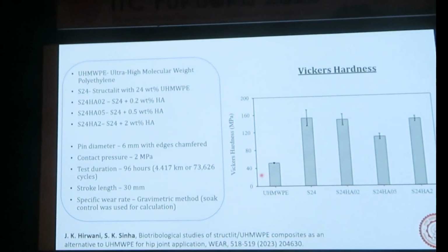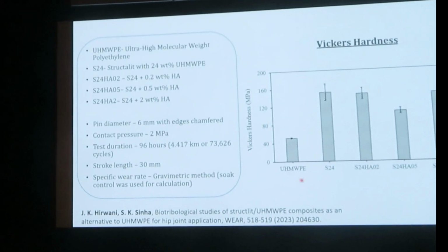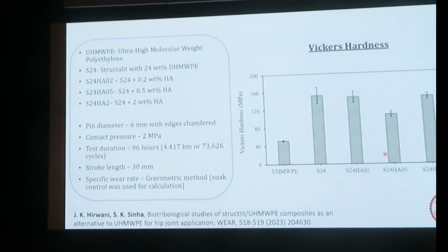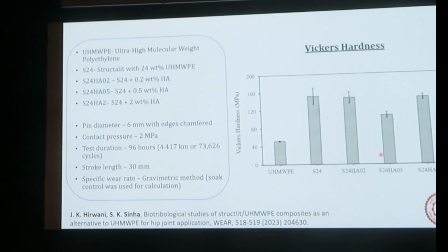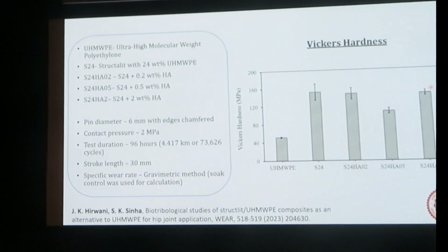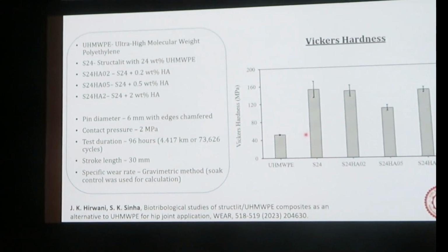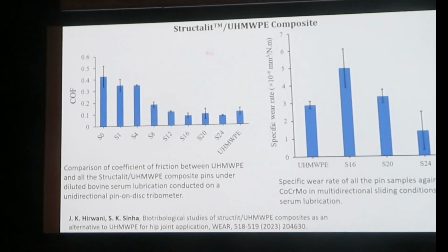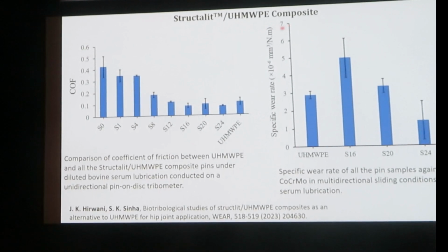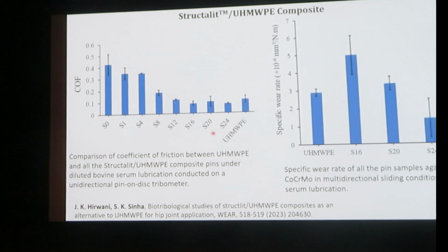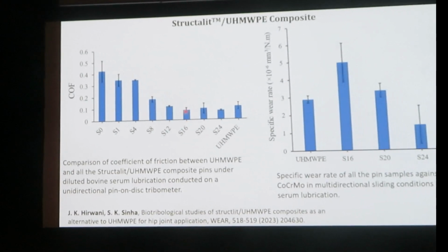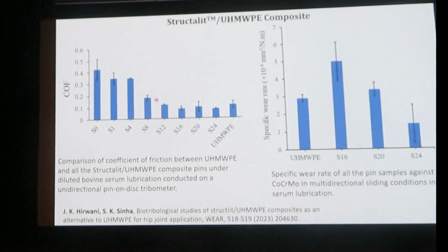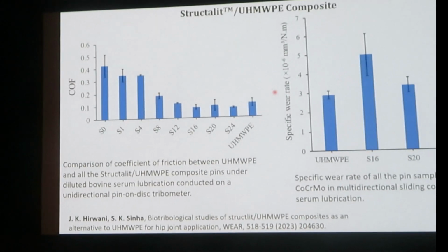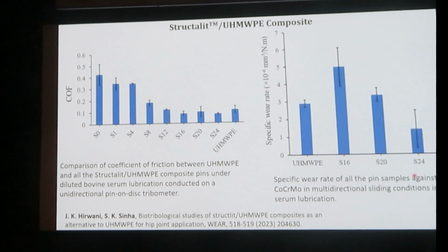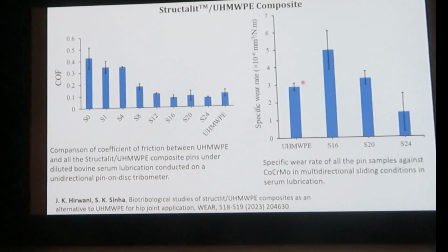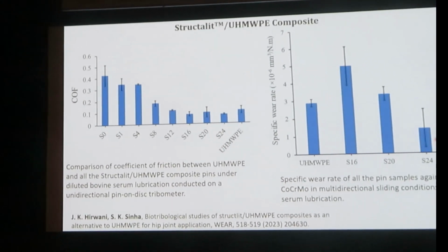So, some hardness tests. Hardness test is a good indicator, but definitely not the final indicator that the tribology will be good. All these compositions have given better hardness compared to pure UHMWPE. I will show you Structalit with UHMWPE particles. About 24% has given the best result. In the bovine serum lubricated case, the coefficient of friction you can see is lower even compared to pure UHMWPE. And the specific wear rate is also lower compared to pure UHMWPE. So in general, this composite gives a better result.